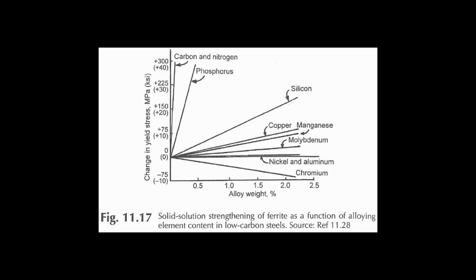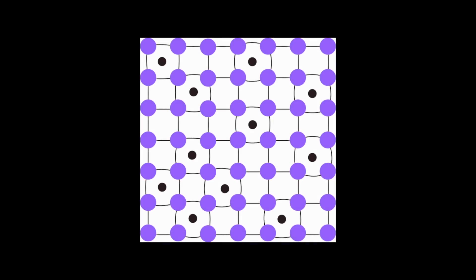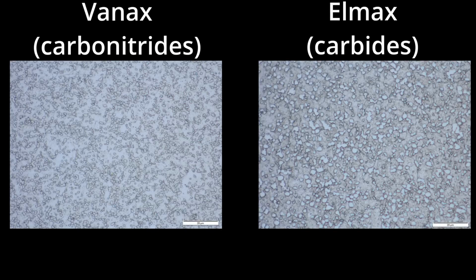Is that like the only other element that does that, inside the iron and the steel? Yeah, it's the only one I know about, unless there was one in metallurgy school I didn't hear about. I mean, other elements can increase strength, like phosphorus is a pretty good strengthening element. But all the other major elements we use for strengthening steel are substitutional elements, meaning they replace iron atoms rather than go in between the iron atoms. Like hydrogen is also an interstitial element that is found in steel, but it's not used for strengthening. Interesting. So it's unique then, carbon and nitrogen are pretty unique. Yeah, and they behave surprisingly similarly in steel. Like carbon forms carbides, hard particles, nitrogen forms nitrides in the steel. So they're almost interchangeable.